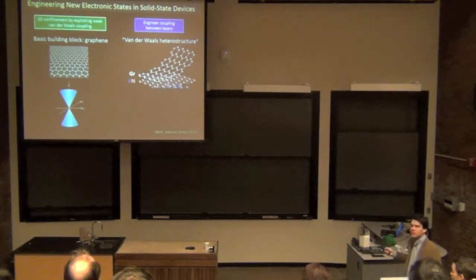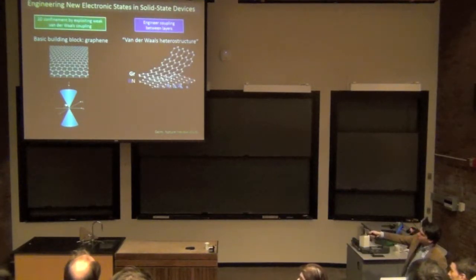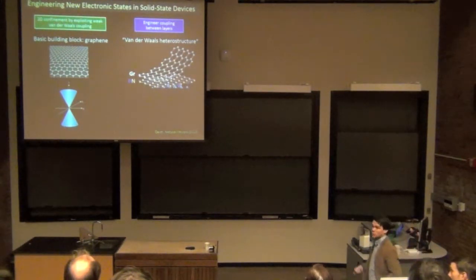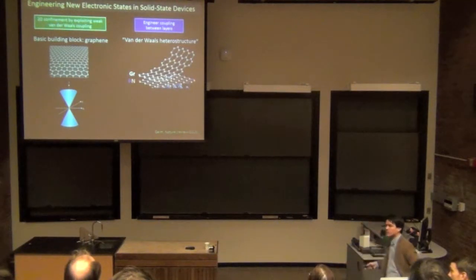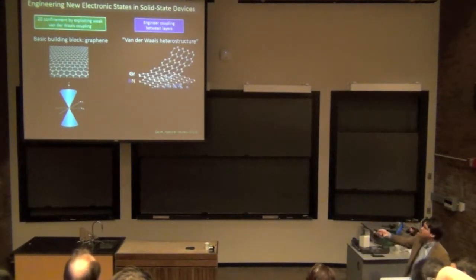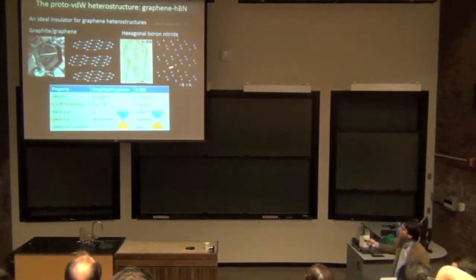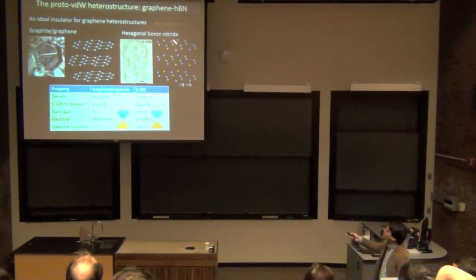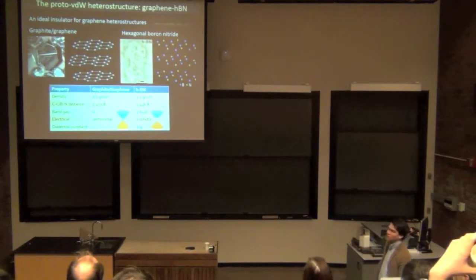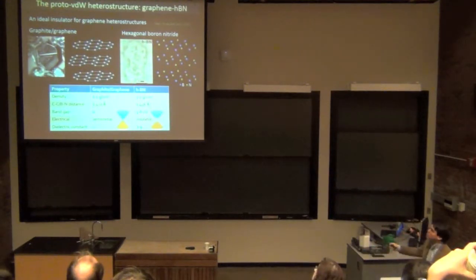And the reason that we're interested in this is that when you make these layered structures, although graphene is a very good semi-metal, as you see here, where the bands touch, what we would like is a very good dielectric, so that we can basically separate the layers, insulate layers from one another, and do that kind of engineering. So it turns out that this structure, or this atom, hexagonal boron nitride, is an ideal insulator for graphene heterostructures.